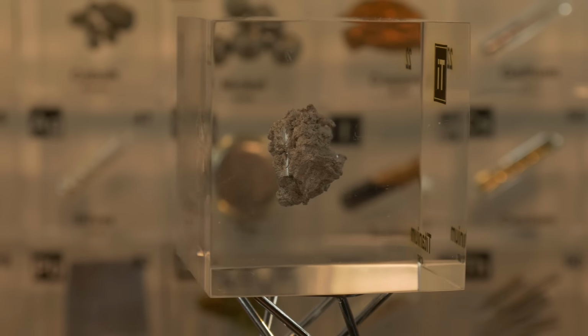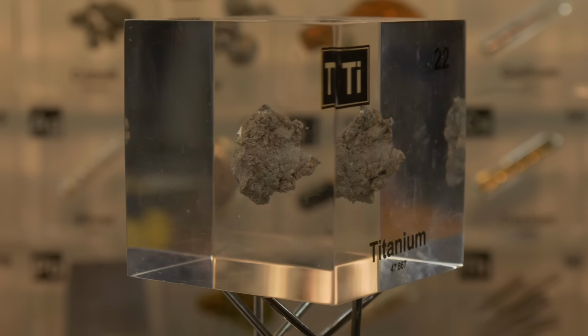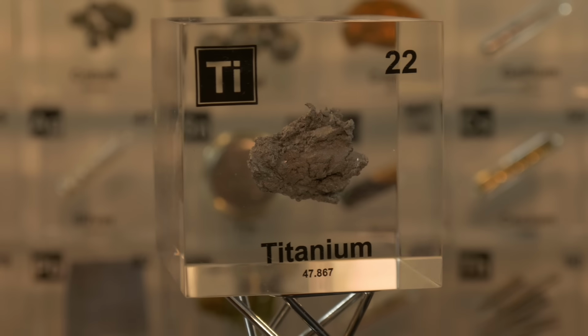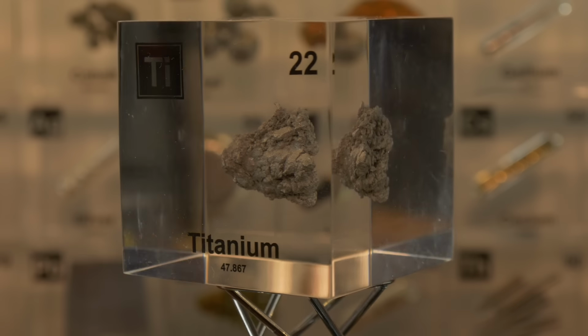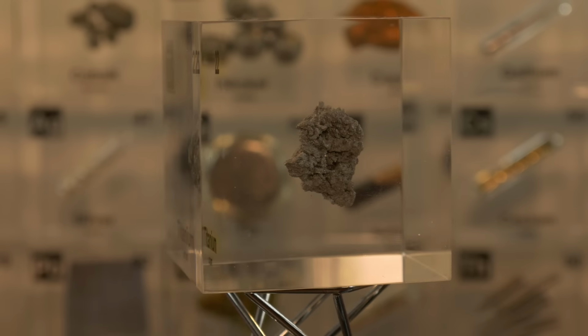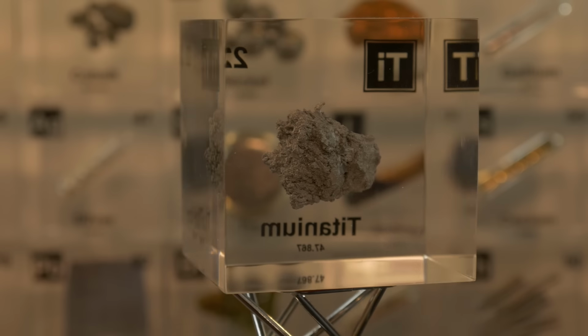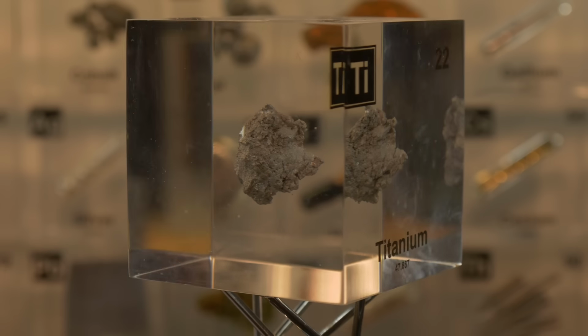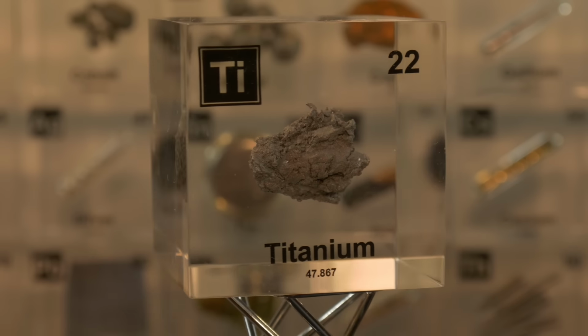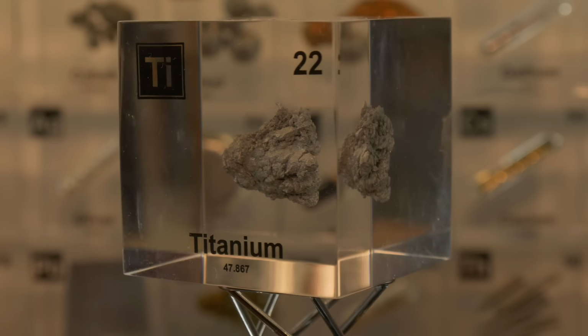Titanium is a hard metal, though not the absolute hardest. Some heat-treated steels or specialized alloys can be harder, meaning more resistant to scratching or denting than titanium. However, titanium is hard enough to resist many forms of wear and tear. Despite its toughness, titanium can be ductile, meaning it can be bent, formed, or drawn into a wire, especially when it's very pure and handled in the right conditions. However, one quirk: titanium's ductility can be reduced if it has oxygen or other impurities in it. High purity titanium in an oxygen-free environment is quite ductile and easy to work.